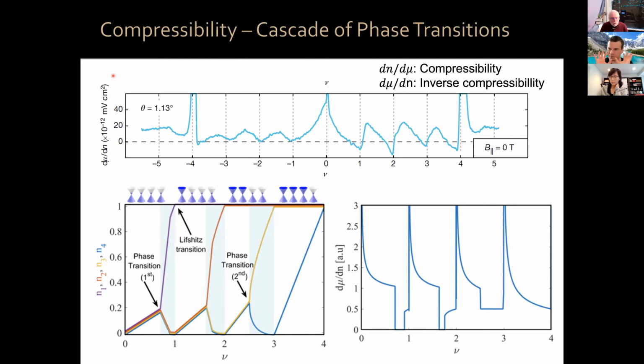In a simple picture, to zeroth order, we understand now that the following is taking place. As you start from charge neutrality, your system has these 4 flavors that it has to add charge to: spin up, spin down, valley K, K prime, okay? Now, as you add charge to your system, as you increase your filling factor, these 4 flavors start to get filled all at the same time, at the same rate. Now, when you are near total filling factor 1, meaning each of these flavors is near 1/4 full, the system, due to strong Coulomb interactions, decides to spontaneously flavor polarize, sending all of the charge carriers into one flavor.